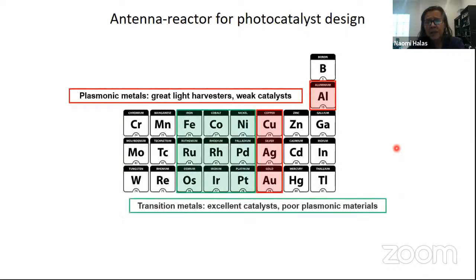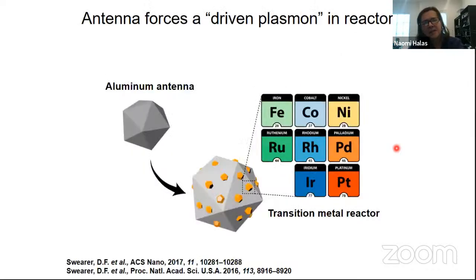So if you talk to catalysis people, they'll say, oh, look at the transition metals. These are the ones that bind strongly to adsorbates. This is how you really want to do catalysis. So how could we possibly combine both of these ideas? We thought we could do it in a relatively simple way. Here we have aluminum. We'll start with aluminum. It's a very good antenna. And if we put small islands on the surface of aluminum that are reactive, then we can perhaps do the experiment.